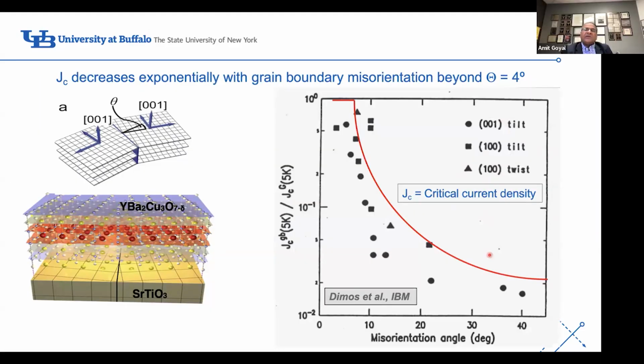So there was this beautiful experiment done at IBM. They took a strontium titanate bicrystal. Bicrystal is one where you can define the grain boundary misorientation to whatever you like it to be. And then they grew the superconductor, the 90 Kelvin superconductor, atom by atom, such that the atomic structure of the strontium titanate was replicated in the superconductor. So now we have created a grain boundary of a certain misorientation in the superconductor, and now you can pass a current through it and plot the amount of current you can pass through this grain boundary intersection divided by the amount of current you can pass within the grain.